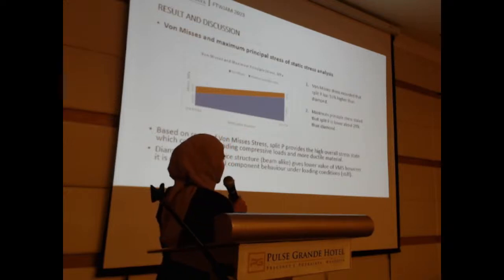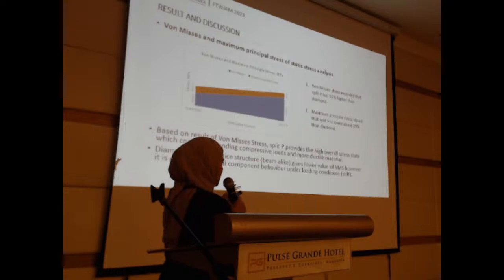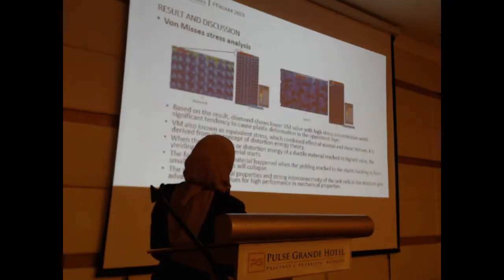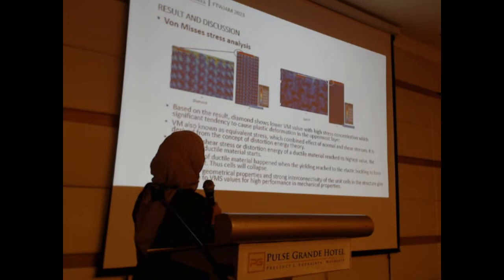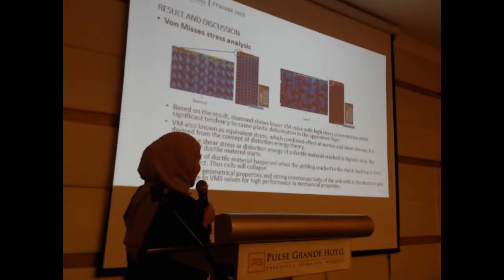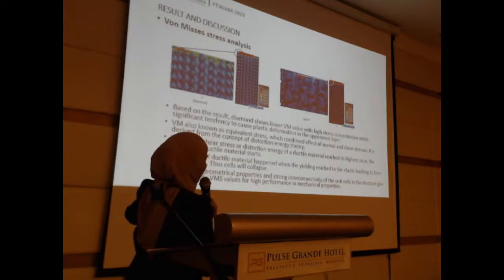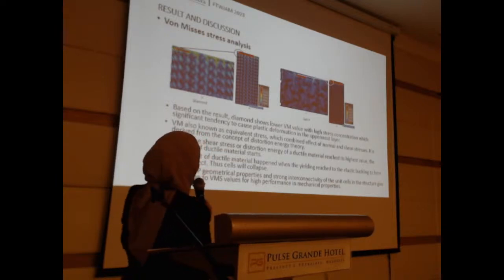Meanwhile, the diamond-shaped lattice structure gives a lower value of von Mises stress. However, diamond is very good in structural component behavior under loading condition. That means diamond is stiffer than the split P. Okay, based on the result, diamond has a lower von Mises value, but it has high stress concentration with significant tendency to cause plastic deformation at the uppermost layer.